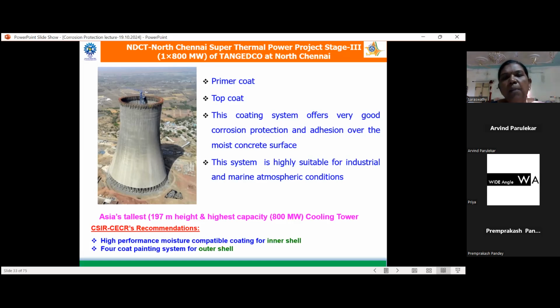We recommended using the high build epoxy developed by CECRI, a moisture compatible high build epoxy, for the inner shell, and for protecting the outer shell, we recommended the 4-coat painting system developed by us. They have implemented this technology, and it has been commissioned recently.